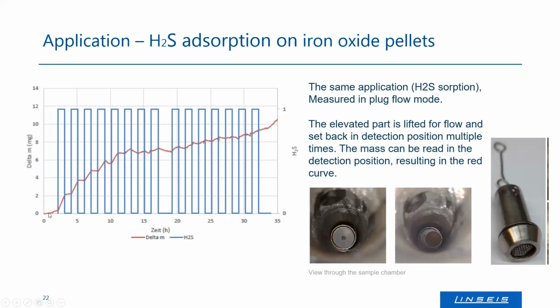Out of that, you get this dark purple or dark red weight increase curve that gives you an idea how much gas is absorbed. And finally, after a certain time, you find a kind of plateau, and you could go into the regeneration phase. And this is how a plug flow reaction would be performed.